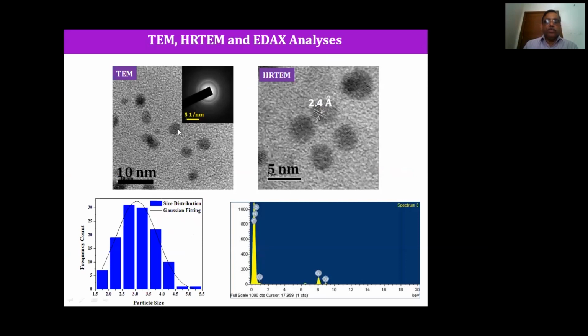When you look at the TEM analysis, we get a size around 5 nanometers, somewhere in the 3 to 5 nanometer range. You can see the average size coming up.